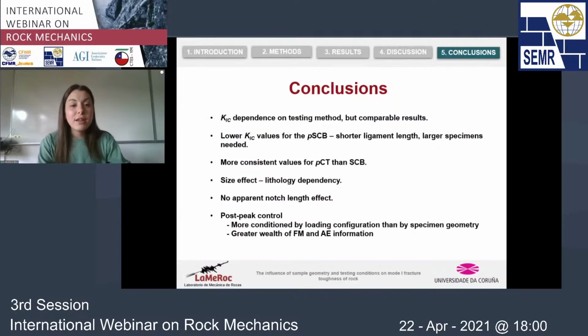So to conclude, we have observed that there was a dependence of mode 1 fracture toughness on the testing method, but that for the SCB and the PCT, the results were comparable. We have also observed lower values for this alternative new method, the pSCB, probably due to the shorter ligament length. So probably in this case, we would need a larger sample to obtain more comparable results.